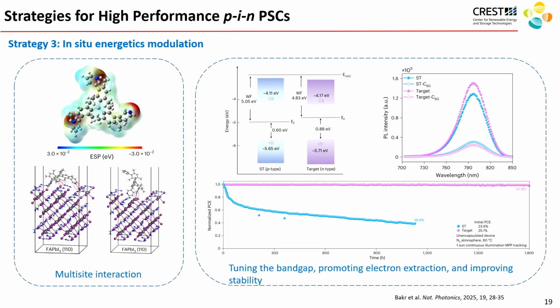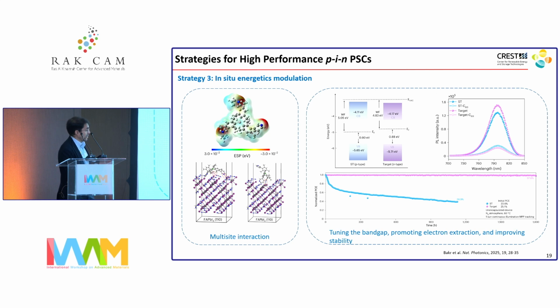You also are seeing now a lot of work on aligning the energy work functions of the different layers, because you want to maximize charge extraction. And so you have to be able to control the interface between the perovskite and the electron transport and hole transport layer very well. And we're seeing methods being used to introduce additives that could in situ control the work functions of the perovskite layer and align them with the work functions of the Fermi levels of the electron transport layer and hole transport layer. And that leads not just to better efficiency, but also promotes better electron extraction and stability.